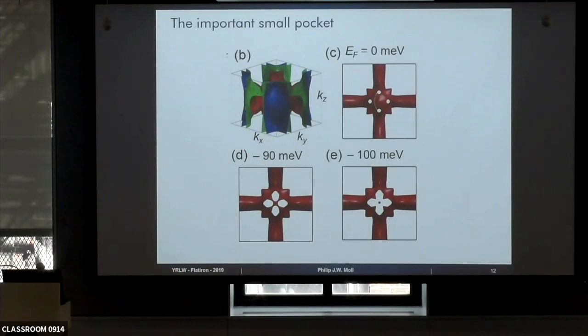To give you an impression of the Fermi surface, you could compute it. There are many, many bands in here. The Fermi surface generally looks very messy. If you want to find the Dirac point, you have to take the central object here, the red band, which leads to these crazy three tubes stuck into each other. And then you have to look down into the tube. If you do that, you will find that the Dirac point is in here. So it's a tiny ball that sits in that tube. That's actually one of the reasons why it was missed before: from the outside you can't see it. It really sits inside of the object.